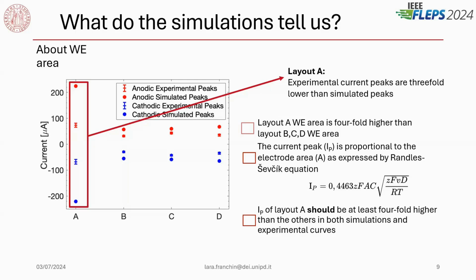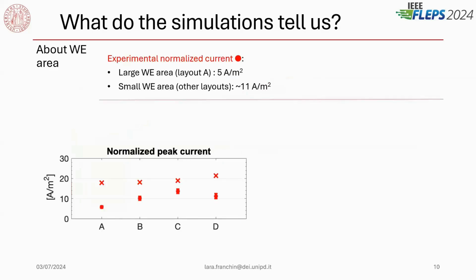Since if we take a look at the Randles-Sevcik equation, the current peaks should be proportional to the area of the electrode, which is 4 times higher than the other layouts. So why is there this difference between the experimental measurement and the expected one, the simulated one? To understand that, we normalized the current, and we saw that with a large working area, the current density was indeed lower than the smaller one for the experimental values.